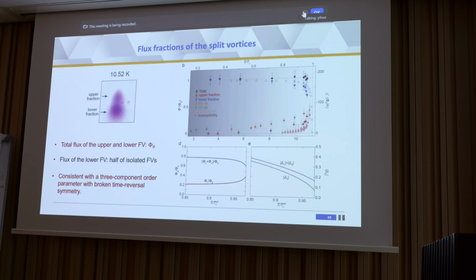And if we do an integral of the flux of these two fractions, we can see it displayed here. The lower fraction is these blue circles, and you can see its flux is decreasing as we increase the temperature. And the upper fraction, these red points, is increasing. But if you sum up the two, shown as these black dots, the total flux is always Phi naught within the error bar. So this seems to suggest that these are the two main components of fractional vortices. Although there could be other fractions in this lower fraction, because when we measure the isolated fractional vortex, the total flux is about 2 times of this lower fraction or upper fraction here.